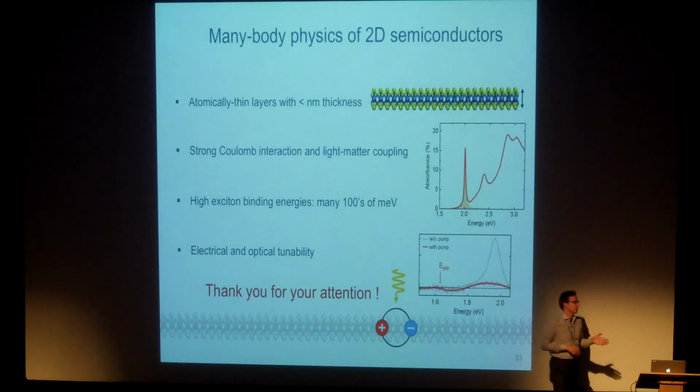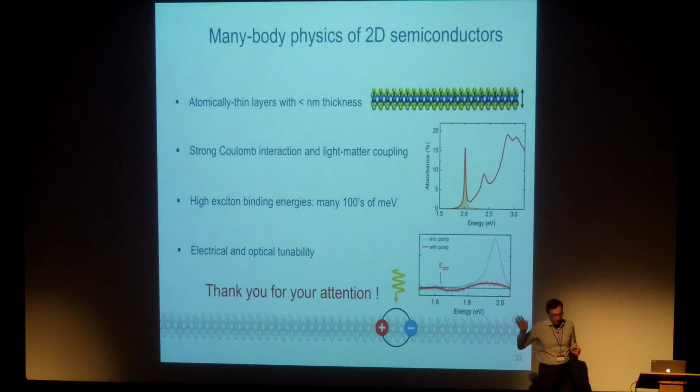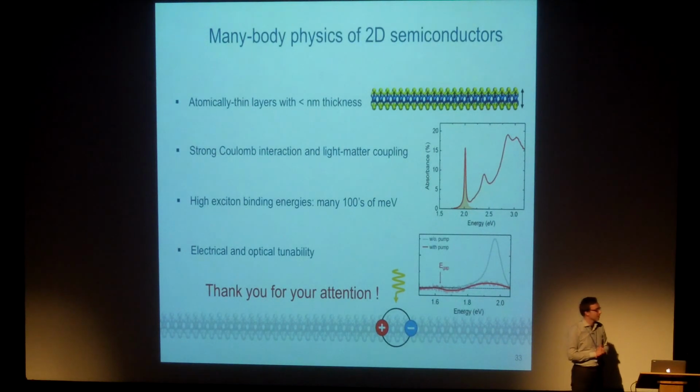And the material will heat up. Within this time, there are phenomena like Auger recombination, which are quite efficient at this density, which will very quickly get a lot of phonons into the system. That means that such an experiment will easily heat up the lattice by maybe 100 Kelvin for these conditions. In a more gentle experiment with, let's say, microjoule pulses, you will get just maybe 10, 20 Kelvin. Of course, it depends on the temperature.